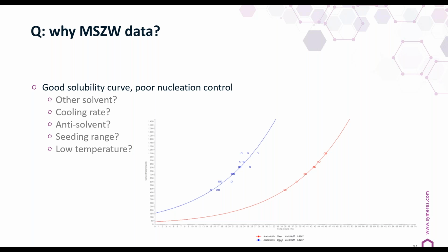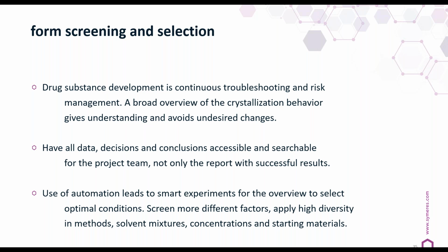Going to below 0 temperatures is costly at the larger scale, easily done at lab scale, but if it doesn't give you more yield, and that shows in your solubility curve when it flattens, then that is the limit. So that is the technical loss that you will have on your yield. It gives you an idea how to set up your process and where you should stop in optimizing that part. Looking at your form screening and form selection, it is always different than you think when you start. So it's continuous troubleshooting. It is giving you a good broad overview, and each time your conditions will tell you where your optimal is, and each time it will be a different optimal when you have a different compound.